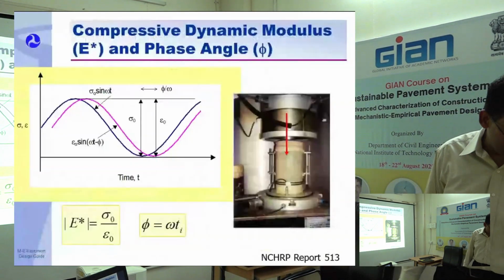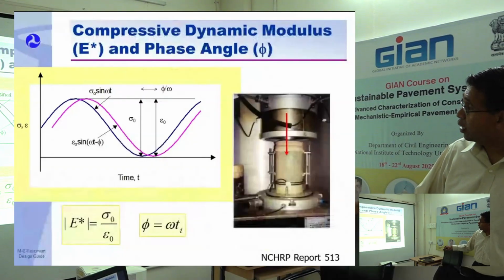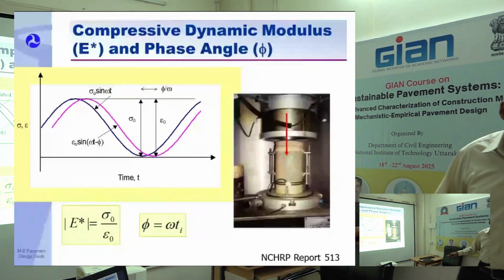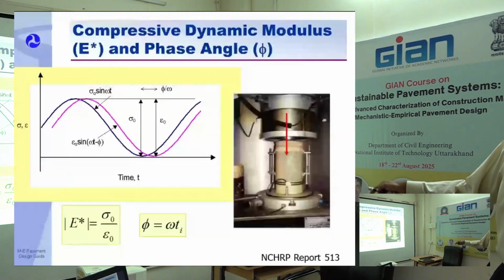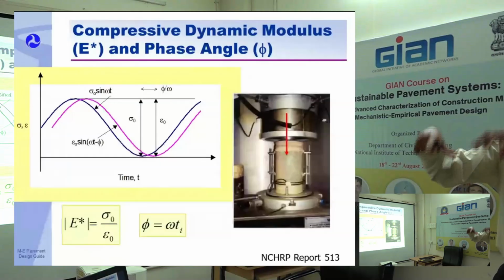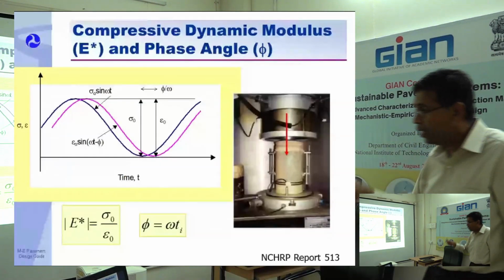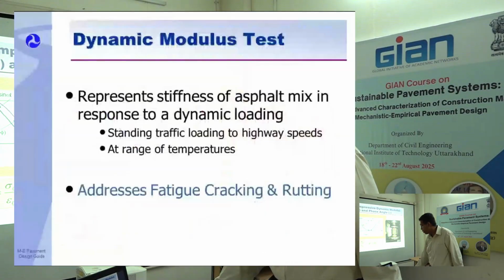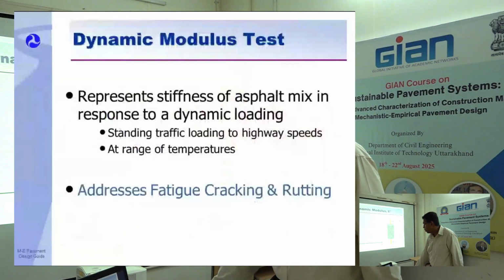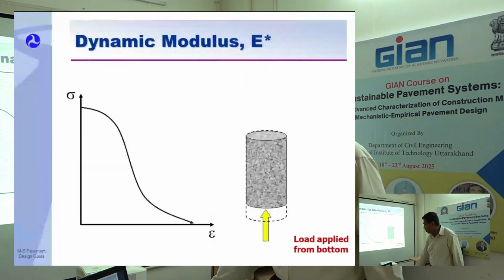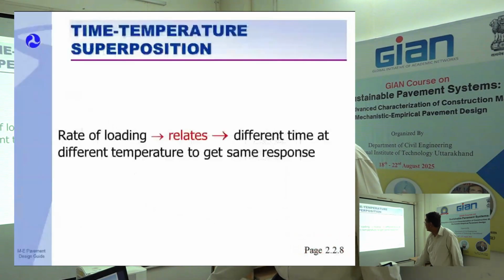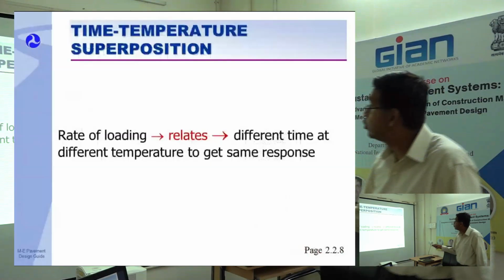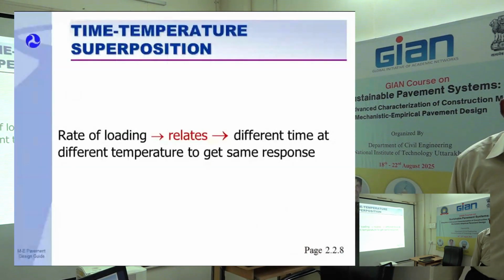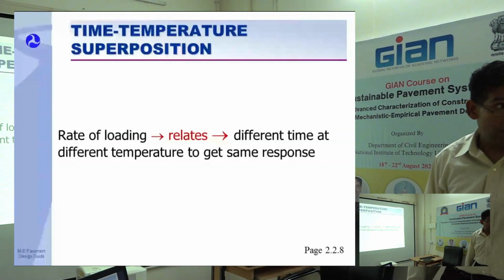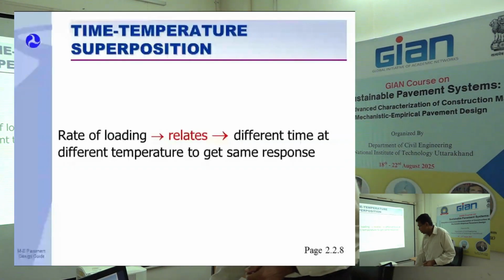You have to do a sinusoidal test, and then you get sigma over epsilon, and you get elastic modulus. Right here, you don't need any confinement. It's a bound material. You have to put sensors in each direction, 3 sensors, and it gets your strain value. Here, load applied. Right here, test for strain. Rate of loading relates to different time at different temperature to get the same response. That's the same thing. I can superimpose temperature and load of testing at the same response.